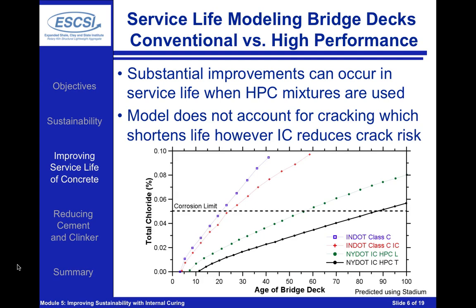The first thing that we can notice when we look at the internally cured concretes in a conventional system is that we would have about 20 years before the concrete begins to go into corrosion. Now, one of the interesting components of this is this model that we're using here assumes that the concrete is completely uncracked. So we can see a slight benefit when we use internal curing going from maybe 18 to 22 years, but we're really not accounting for the major benefit of reducing the overall cracking in the concrete system.